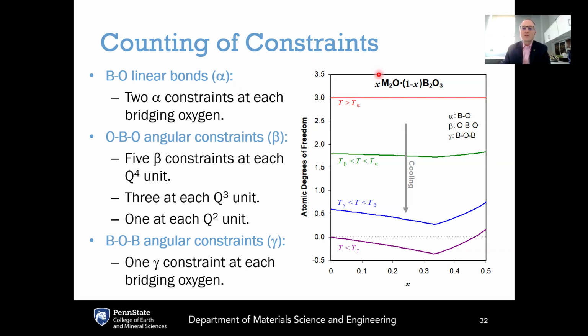That means that regardless of the composition, there are three atomic degrees of freedom per atom because there are no rigid constraints. So all three degrees of freedom, the X, Y, and Z degrees of freedom, are all available to the system. But if you cool the system where the temperature falls below T alpha, that means that these linear bonds are now providing rigidity in the network. And that means we go from the red line here down to the green line. The green line shows temperatures that are less than T alpha.